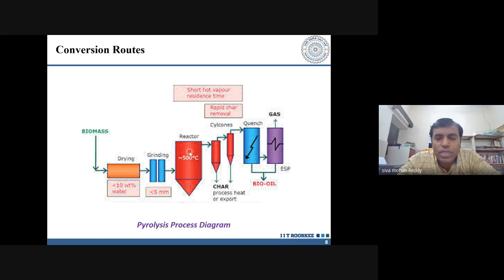So another kind of process that I have already mentioned is fast pyrolysis. You can have very high heating rates, more than 50 degrees centigrade per minute, so there you also have very high yields of bio oil. But when you have a slow pyrolysis, you have less bio oil and gas, and your main focus will be the solid biochar that you are going to get, right? So that's how the pyrolysis process has been classified, depending upon the temperature and the heating rates that have been mentioned.